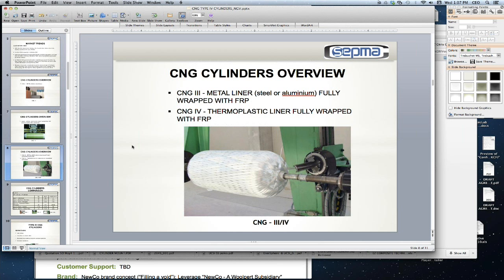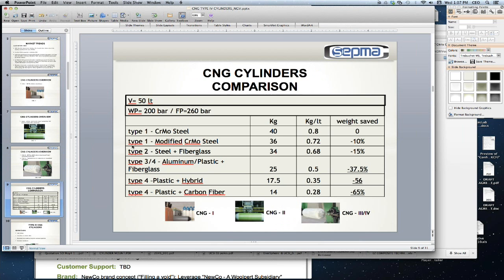Likewise, in the Type 4 technology, now we're using a thermoplastic liner, typically polyethylene, high-density polyethylene or a nylon, and equally fully wrapped with FRP. So to summarize, if we take a 50-liter tank, which is about 15 gallons, and we compare the weight based on the several technologies, you can see that we go from 40 kilograms, or about 88 pounds, for a Type 1 system,